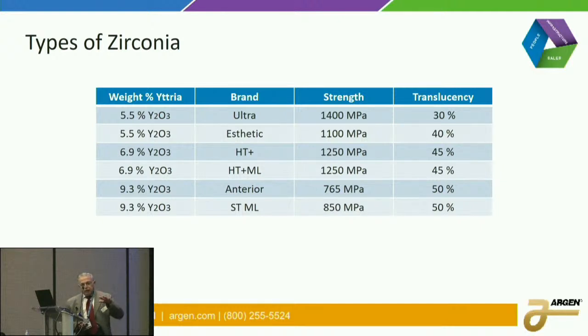And now you're starting to see a material that could actually be somewhat close to a natural dentition, be colored to look like a natural dentition. Then when we developed this HT Plus, our idea was to keep the strength the same, but increase the translucency. And we actually wound up with a double benefit here because the processing modification actually increased the strength over the aesthetic materials while we still got a higher translucency. So because of this result, on the research side, we actually dropped the aesthetic brand from sale.